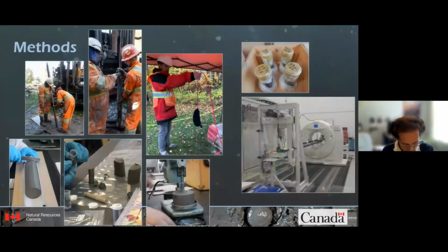So the methods we used: we drilled in the fall of 2019, attempting to collect relatively undisturbed continuous core in Shelby tubes using a piston corer or an open tube sampler. When these didn't work, we used a split spoon sampler. We installed piezometers and vibrating wire piezometers at both sites. We carefully preserved the cores on site in wax. We drove them to Quebec City and scanned them in the CT scanner. We brought them back to Ottawa, and we've been extruding them, sampling and subsampling them, and running analyses on them, such as, in this case, a fall cone analysis on the fresh sample.